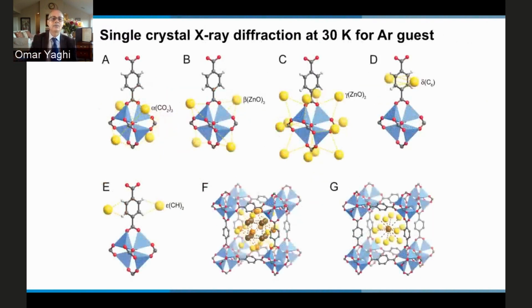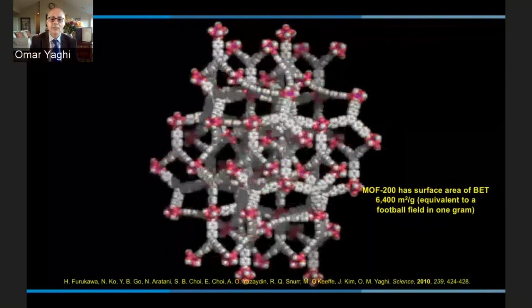per gram. And you see here that all the yellow dots are either argon or nitrogen. And you see that everything you're looking at in a MOF is an adsorptive site. The faces of the octahedron, the edges of the octahedron, as well as the faces of the tetrahedron of zincs, they're all adsorptive sites, and all of them were determined, including the faces of the six-membered rings, as well as the edges of the six-membered rings. All of these, we found argon atoms interacting with them as adsorptive sites. And we also went beyond the monolayer and localized some of the argon and nitrogen atoms that are filling the pores. So what this study says is that everything you're looking at in a MOF is an adsorptive site.